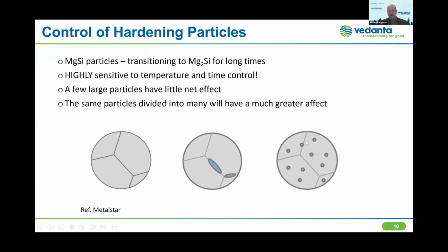Contrasted with, on the right here, if we were to take the same amount of magnesium and silicon and control how that comes out in the matrix of the aluminum, we would have many fine particles. And this is much more effective for strengthening. This is actually what we're trying to accomplish in aging, which we're not going to talk too much about. But in the extrusion process, what we're trying to do is maintain this, and we're trying to avoid having these large particles come out, which are then unavailable for hardening, for forming small phases in the aging. So again, we want to control how this comes out and not let the process just happen to us, but take control.